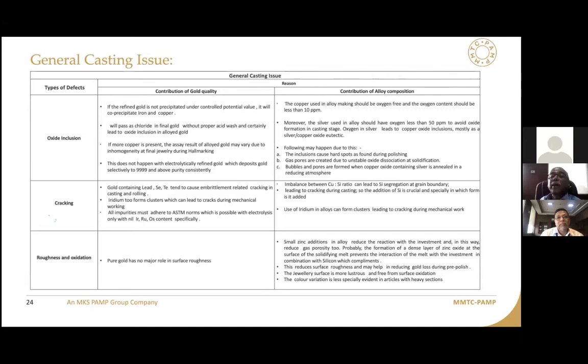Now, from the alloy, again, I say the copper should be free from oxygen, less than 10 ppm, and the silver should have less than 50 ppm. If you get oxygen, which can lead to copper oxide, it can form gas pores, it can form inclusions, and even in mechanical working, when you want to do annealing, these oxides can get converted and you will get pores during the hydrogen treatment or ammonia treatment.